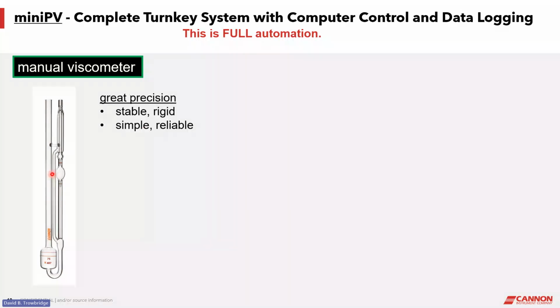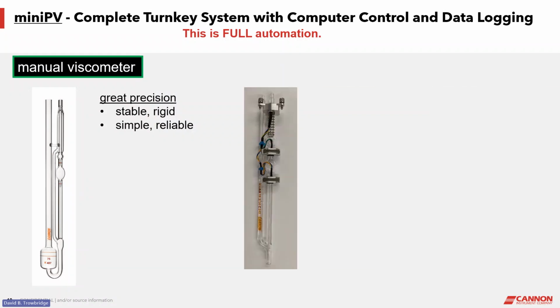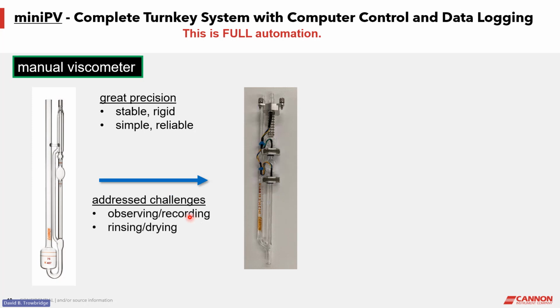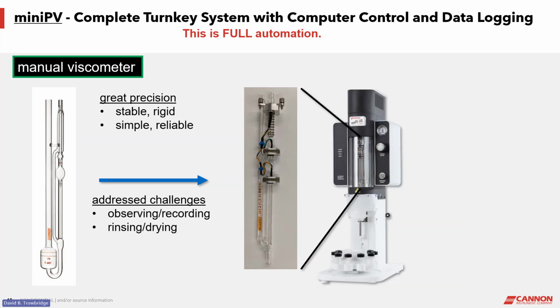But we start with the manual viscometer, as I said, because it has the great precision, and we want to retain these features. So as I said, we built an automated version of that viscometer, and in the process, we addressed 2 of the disadvantages. Observing and recording the time now is automated because of the sensors, and rinsing and drying the viscometer now is automated because we have a flow-through design. And then this viscometer tube is put inside a bath built into the instrument. So the automated mini PV instrument has the bath constructed into it, and it also has the auto sampler with vials that holds 10 different samples. So we have 10 positions.